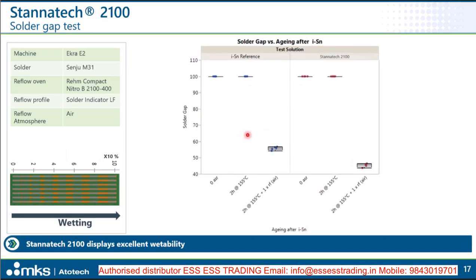And finally, the solder gap test. This is another wetting test where we apply solder on a different test structure. We have rectangular long pad lines, and these lines are printed with solder depots. We apply the reflow aging, and then we measure how long the solder depots manage to connect. Again, the higher the value, the better the solderability, or the solder wetting. And you see again very comparable conditions for the immersion tin reference and the Stannatech 2100, and they are all again passing the target requirements.